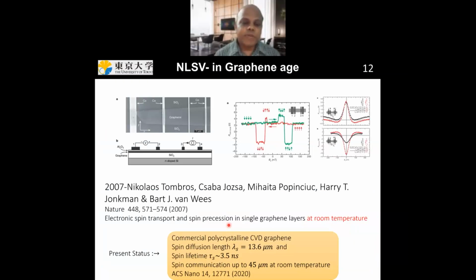With time, there was a big revolution when graphene was discovered. People soon realized that graphene can be a very ideal material for spin transport. The first non-local spin valve device with graphene was fabricated in the year 2007 in the Bart van Wees group again. They could show the spin transport at room temperature. Right now, the best record for spin diffusion length in CVD graphene is around 13.6 micrometers. In fact, one can observe spin signal up to 45 micrometers. So this gives a lot of opportunity for this kind of devices for practical applications.